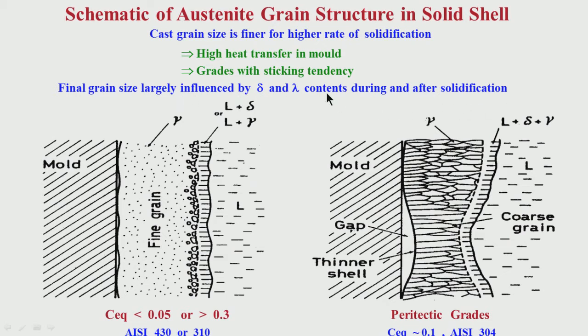during and after solidification. Because if you have delta during casting and also at temperature lower than the casting, that means for very low carbon equivalent or say 430, where the delta to gamma transformation is taking place at quite lower temperature even after solidification, delta is present for quite some time for quite a big temperature region. So, there is a possibility of grain coarsening of delta. So, there we have to be a bit careful. In such cases the earlier will be the onset of austenite, finer will be the delta grains.